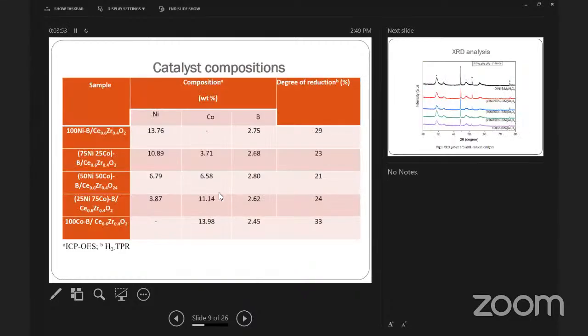Here we did ICP for evaluating the concentration of nickel, cobalt, and boron. As we added 15%, it's around 15% with the ratio. We have prepared 5 types of catalysts: the first one is 100% nickel, the second one is 75% nickel and 25% cobalt, the third one is 50-50, the fourth one is 25-75, and the last one is 100% cobalt. Accordingly, we got the concentrations and also the boron concentration. We added 3%, so it's almost 3%, but not exactly.